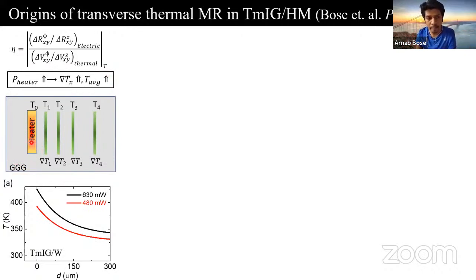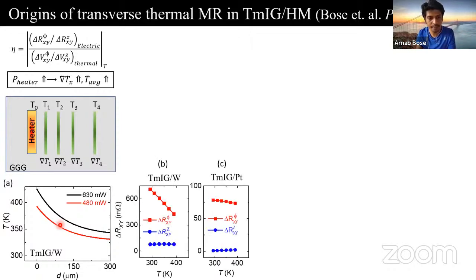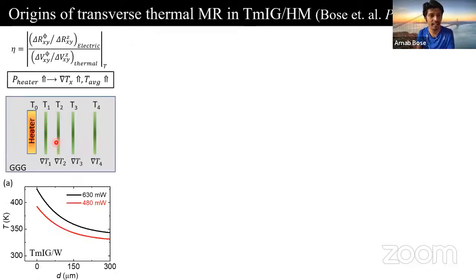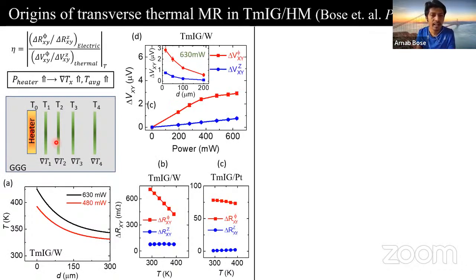We find that whenever we try to create an in-plane thermal gradient, the local or average temperature of the sample increases because we heat up the sample. And the increase in temperature could be very substantial. It can be more than 100 degrees C. So that must be taken care of in the calculation. That's why we also measure the electrical magnetoresistance as a function of temperature. The local temperature of the device is obtained from the resistivity of the devices. And here I show the thermal voltage as a function of heater power, suggesting that as we increase the heater power, the thermal voltage increases, which is quite obvious. And this data shows that as we go away from the heater, the voltage signal goes down. That is also quite expected. So now we have all the data to analyze this parameter for a given temperature.